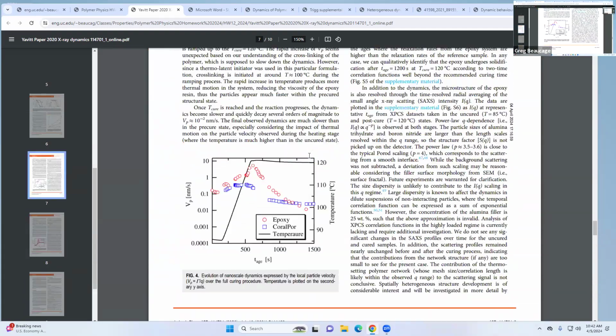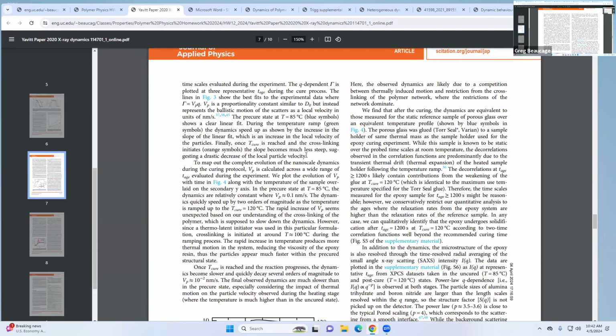Some fun stories about this. These experiments are pretty quick. We're looking at behavior over a couple thousand seconds, but you have to remember we're taking thousands of frames at frame rates of 10 to the 2 to 10 to the 3 hertz or something like that. Literally, each one of these experiments is about a terabyte of data. And we were doing like 2 or 3 days worth of these experiments. The amount of data in these experiments is absolutely insane. I collected all this data in probably 2 or 3 days. It took me 6 months to analyze it and write the paper because it's that data rich and intensive. But that's why it's really fun. You don't have to do a lot of work, and then you get a ton of cool information.